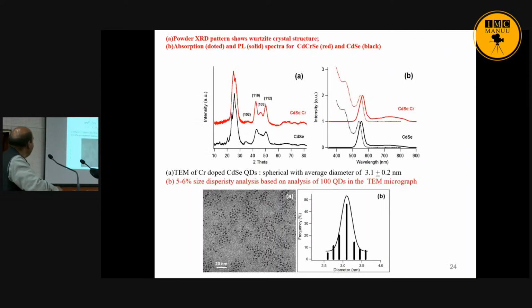Then you can see the XRD here. You can see the doped or undoped spectra; you are getting this peak here. It's a very good peak. This is the quantum confinement for the doped sample. This is the TEM image, a bunch of images here. The particle size is about 3.1 nanometers. So this is coming from this. Then we study.